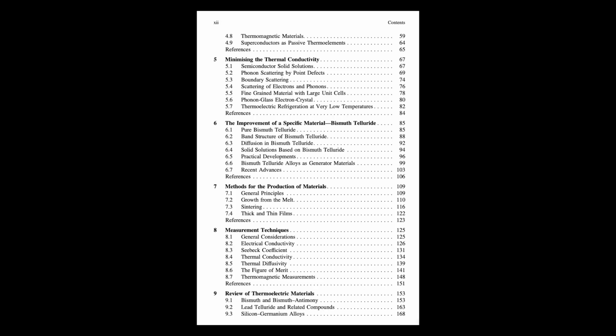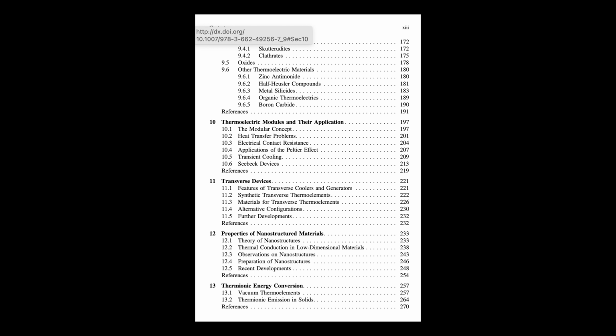Skutterudites often have naturally low lattice conductivity. You can stick guest atoms in the cages, rattlers that vibrate and scatter phonons without messing up electrical conduction too much. Adding pores can sometimes help too, maybe filtering electrons or scattering phonons more. Some filled skutterudites have shown really high ZT values.